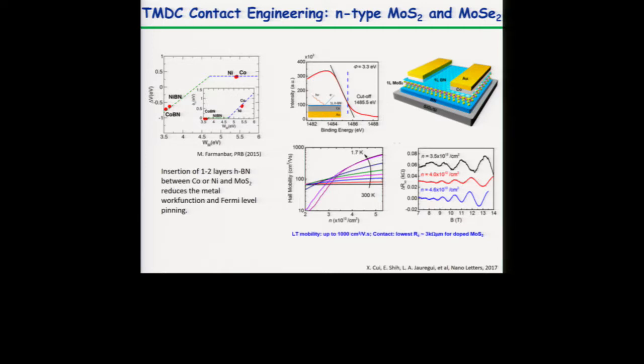Boron nitride is a dipolar insulator, right? It's two different materials, boron and nitrogen. And if you have boron nitride in between cobalt and the TMDC, you end up reducing the work function. Here at CNS, we measured the work function of cobalt with boron nitride, and it's indeed reduced. We obtain a work function of around 3.6 electron volts, so it matches well with the MoS2 conduction band.